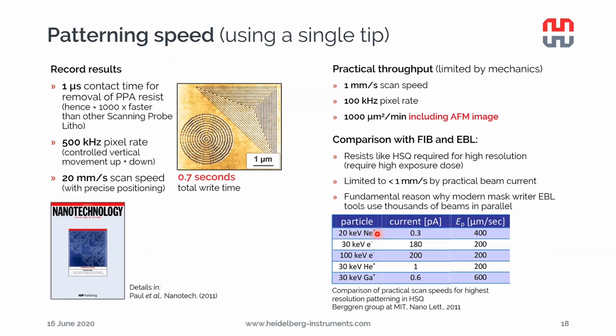Now, finally, the obvious question is, as I have presented technologies for high volume manufacturing, what is actually the patterning speed to fabricate such masters? Practically, the throughput at very high resolution to create masters with a NanoFrazor is about 1,000 square microns per minute. This of course includes the topographical AFM image that we get as a side product of the patterning process. When we compare this with alternative technologies, such as focused ion beam or electron beam lithography, it is pretty much on par. Electron beam lithography requires resists like HSQ, a silicon-based resist that requires an extremely high exposure dose for patterning such high resolution structures, and therefore the scanning speed of the beam is limited to less than 1 millimeter per second.